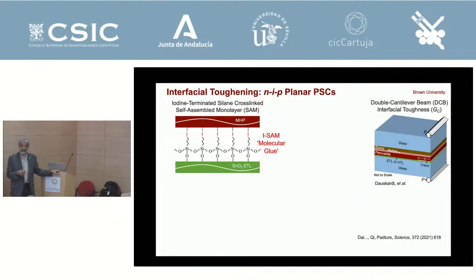And so what we started working on is using what are called self-assembled monolayers, and many of you may know this, self-assembled monolayers. This is a very famous self-assembled monolayer called silane, which is used in fiber reinforced composites. So all fiber reinforced composites, it's sold by the tons. Silica fibers are covered with a silane SAM, and then it's embedded in the polymer, because then you get the bonding between the fiber and the polymer for stress transfer, right? Our innovation here was to terminate this with iodine, and it's called an iodinated self-assembled monolayer. Also, it's short chain, it's cross-linked, right?